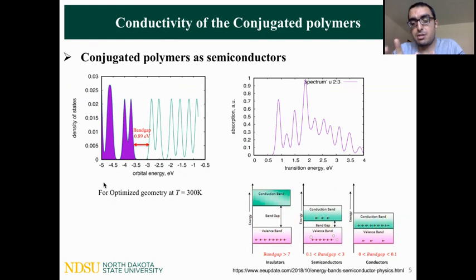Also, the top right figure shows the absorption spectrum. We expect from this plot that the first peak should fall into the band gap, and as you can see, it's around 0.9 for this polymer model. Next, please.